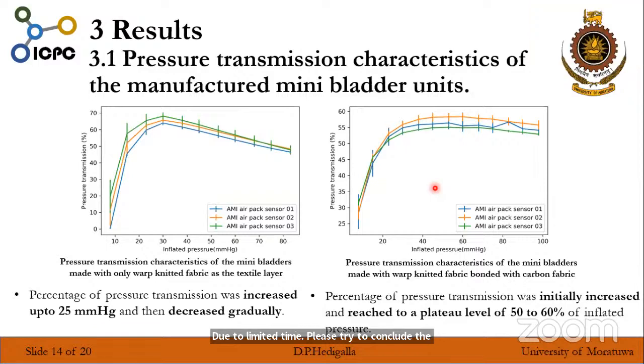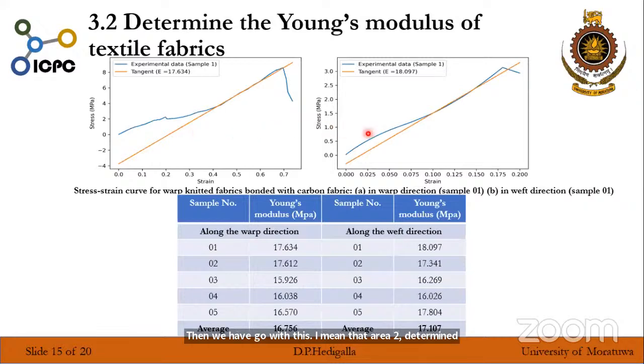Okay. Thank you. Then we go on with this mini bladder array. To determine the material parameters, textile fabrics were tested under ASTM D5035, and Young's modulus was calculated by drawing a tangent line to the stress-strain curve, and those are the results of the Young's modulus.